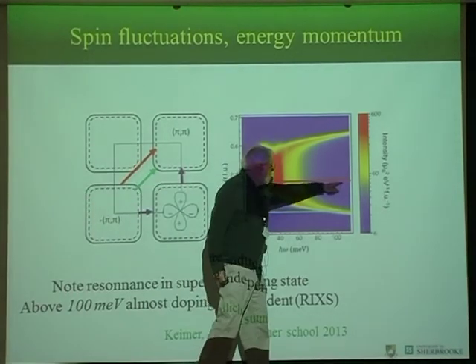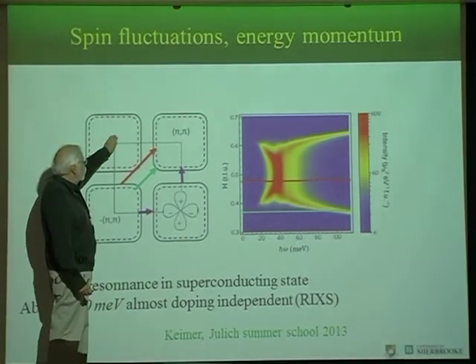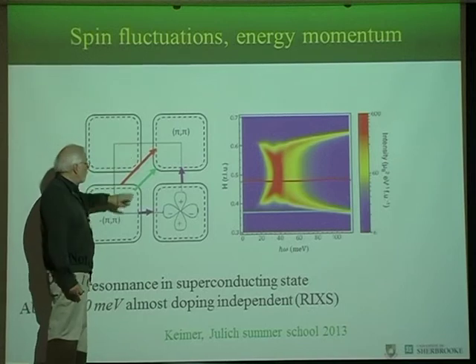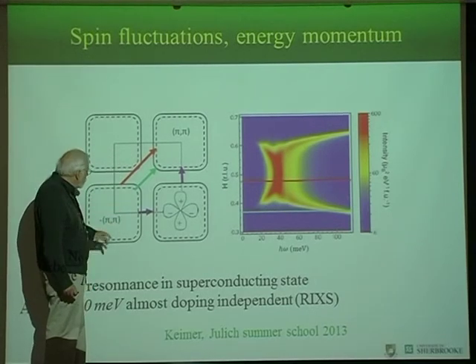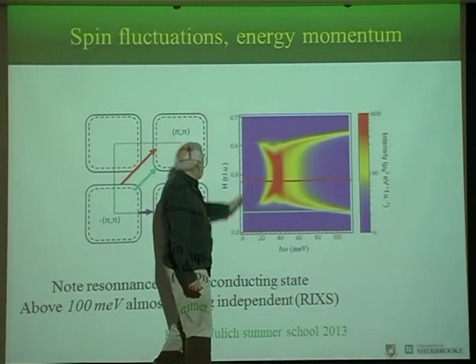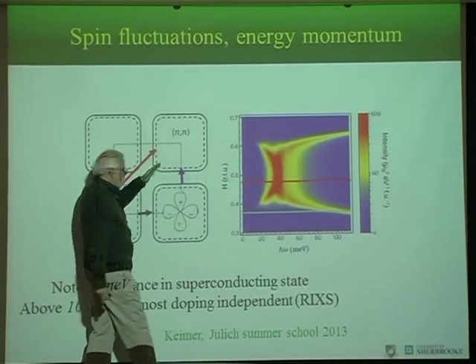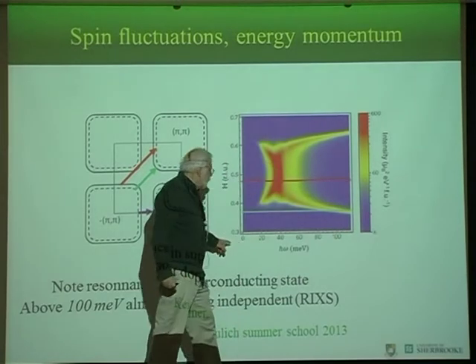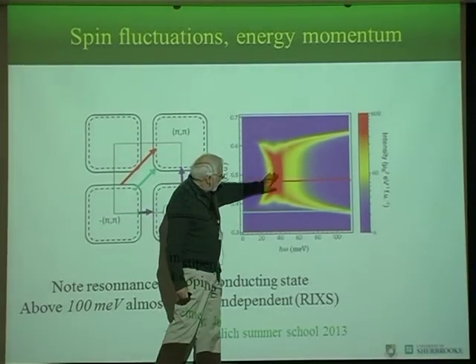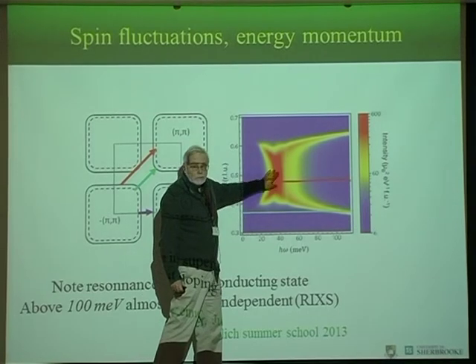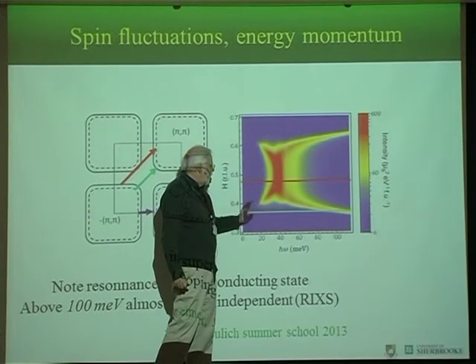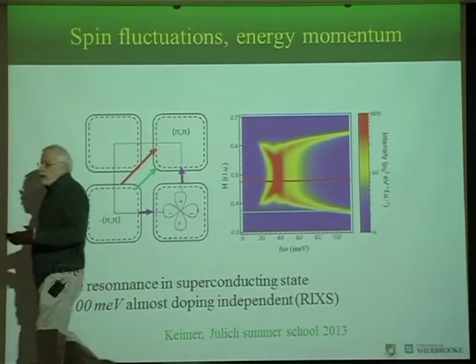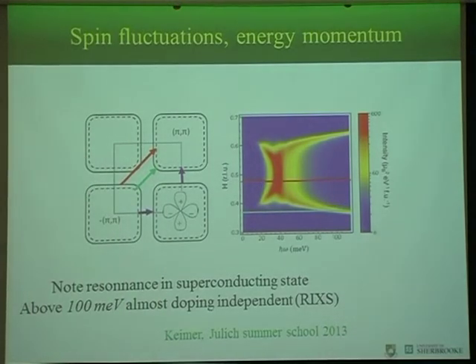So the red line is scanning like this. Now I centered the Fermi surface around pi, so it just looks like a square or some rounded square. H is like that, so you get the red here, the green there. And if this axis is energy, you see in the superconducting state, you get this resonance at 40 meV, and you remove the states here because you've opened a gap. So contrary to the case of electron-phonon interaction, where there's little feedback of the electrons on the phonons, it's not zero, but it's small. Here it's relatively important: the superconducting gap removes the low energy spin waves.